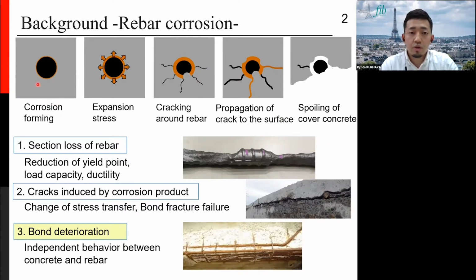After corrosion starting, the corrosion product generates the expansion force and induces cracks in the concrete around the rebar. Once the crack reaches the concrete surface, deterioration factors such as chloride ion can easily penetrate, and the corrosion progress is accelerated. And finally, the spalling of cover concrete occurs, as you know. In this sequence, rebar corrosion causes three main phenomena: the section loss of rebar, the corrosion crack, and bond deterioration.